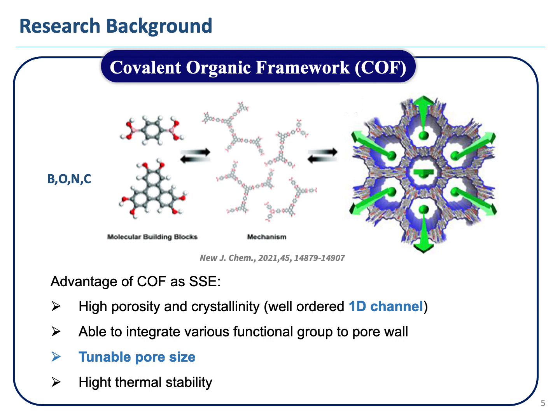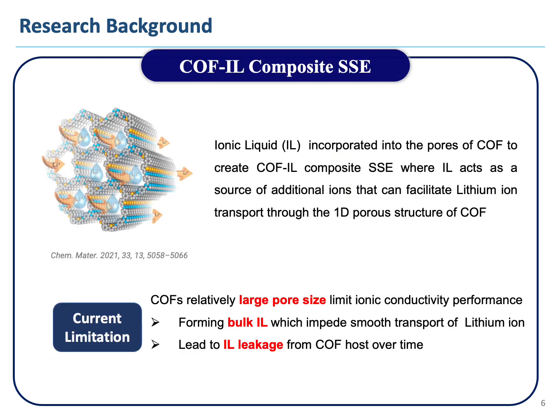Among them, one of the notable strategies is to incorporate ionic liquid into the pores of COF to create a composite material, which we call COF-IL composite solid-state electrolyte. Ionic liquid is incorporated into the pores of COF to create COF-IL composite, where IL acts as a source of additional ions that can facilitate lithium ion transport through the 1D porous structure of COF.